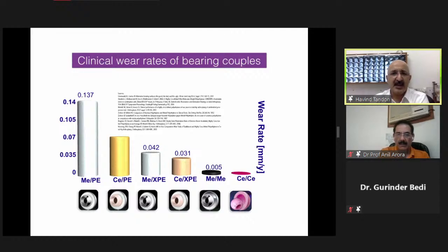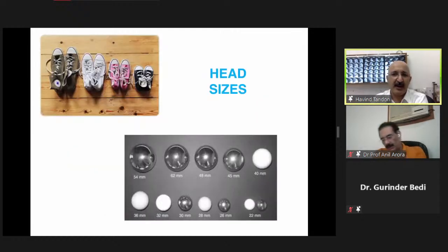If we see the chart, the wear rates of the various bearing couples, the metal on conventional polyethylene was high, and the lowest we are seeing in ceramic on ceramic. But most of our orthopedic surgeons doing joints, it is either metal head on a cross-link polyethylene with vitamin E, or a ceramic on a cross-link polyethylene, which we use, which also have very low wear rate.